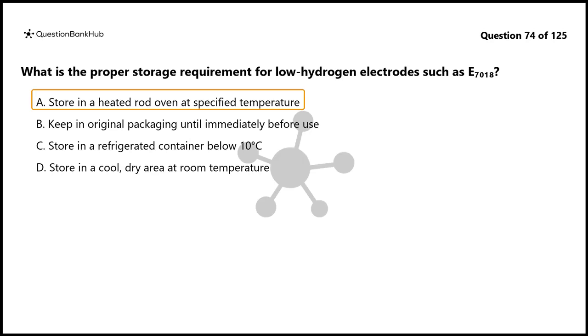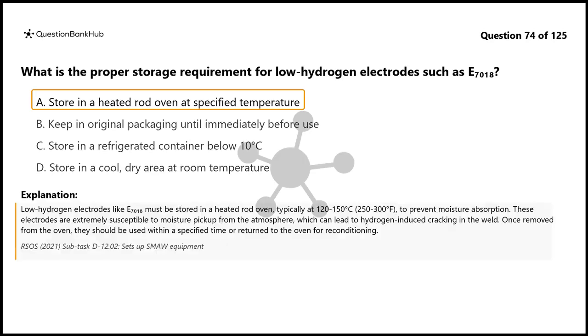The correct answer is A. Store in a heated rod oven at specified temperature. Low hydrogen electrodes like E7018 must be stored in a heated rod oven, typically at 120 to 150 degrees Celsius, 250 to 300 degrees Fahrenheit, to prevent moisture absorption. These electrodes are extremely susceptible to moisture pickup from the atmosphere, which can lead to hydrogen-induced cracking in the weld. Once removed from the oven, they should be used within a specified time or returned to the oven for reconditioning.